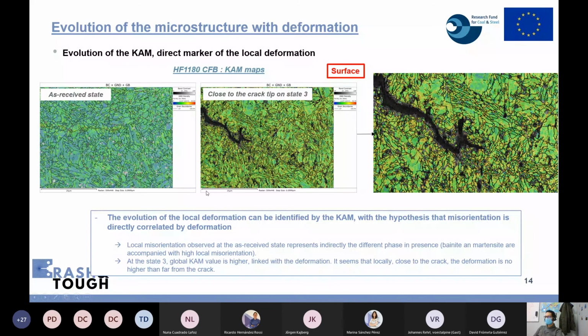So we can see through the KAM maps that between the zone far from the crack and close to the crack, all the surface analyzed by EBSD here is impacted by the deformation, and that close to the crack there is also more deformation. And so we can say that all the phases are impacted by the deformation. So this is a fact.